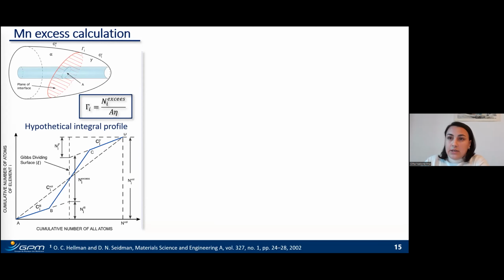So Gibbsian excess is the number of accumulated atoms at the interface divided by the interfacial area. As the APT technique derives a discrete count of atoms in the analyzed volume, it was proposed by Hellman and Seidman to calculate manganese excess using the integral profile that you schematically see on the slide. However, this method requires the definition of the position of the planar interface that is supposed to strictly separate two phases, austenite and ferrite in our case. And this plane is called the dividing surface.